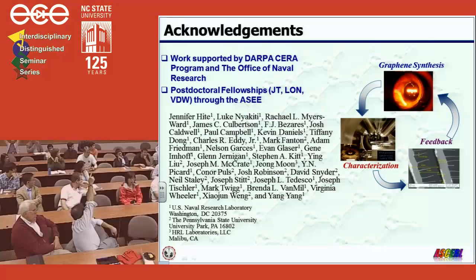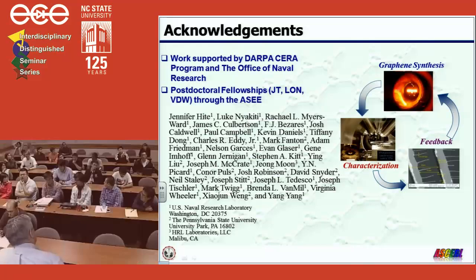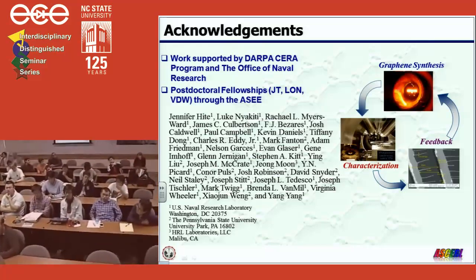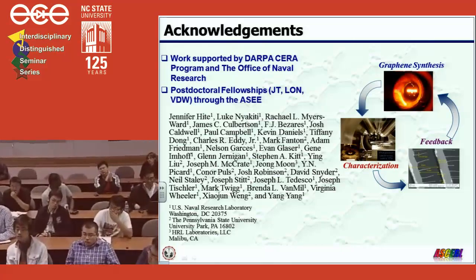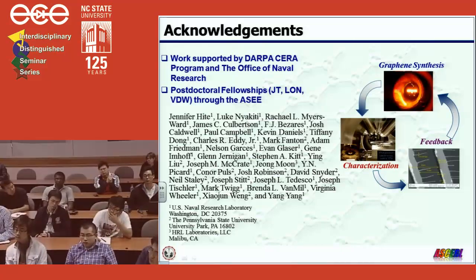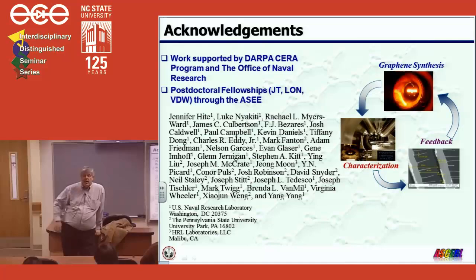Back there? Yeah. So for the silicon face graphene, you have a transition layer, right? Yes. When you lift off the graphene, will the transition layer come up together or no? Oh, that's a very interesting question. We have made attempts trying to peel off graphene on the silicon face material. They have not been successful. We have been able to peel it off the carbon face. That has been successful.